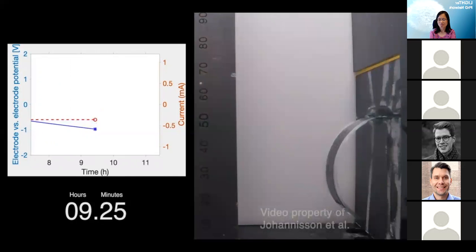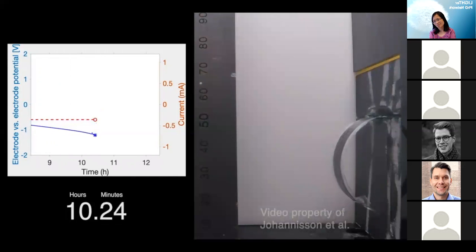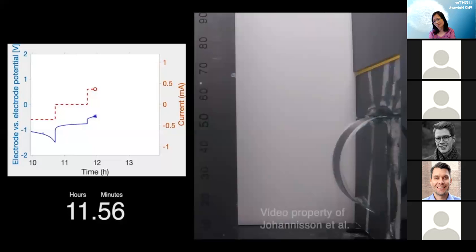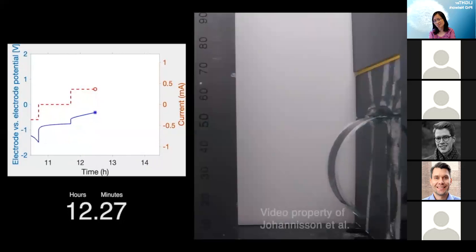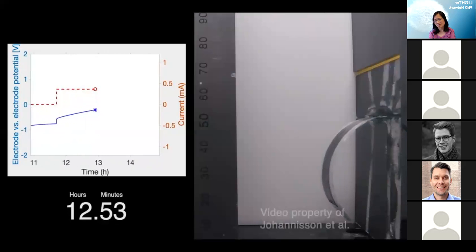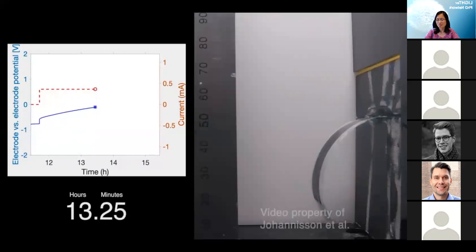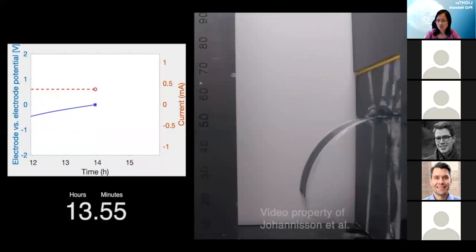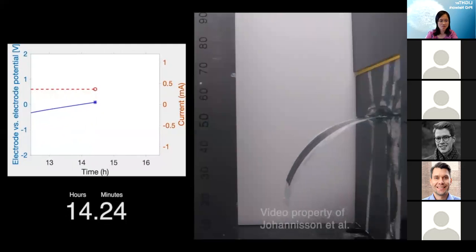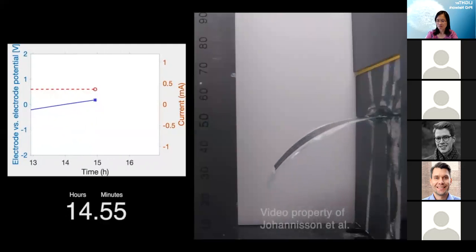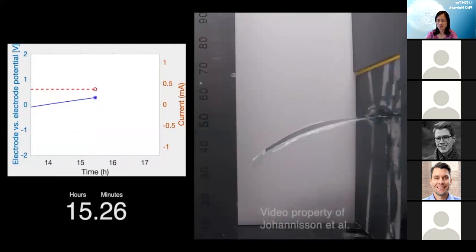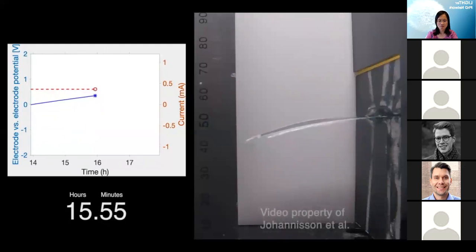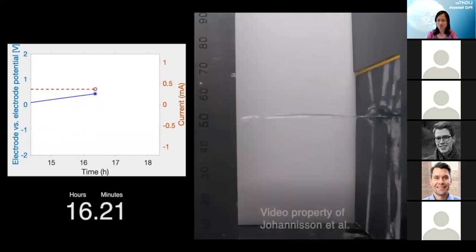Here we see the material forming a half circle and touching the wall, after which the current is reapplied. And this is bringing the material back to center. Between each step, we've seen an hour-long pause where the 2 electrodes are disconnected. The material is during this pause staying deformed, and this is an important feature of the material, which is called zero power hold.